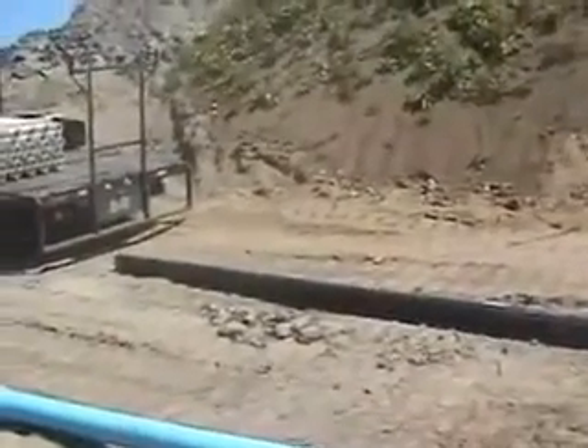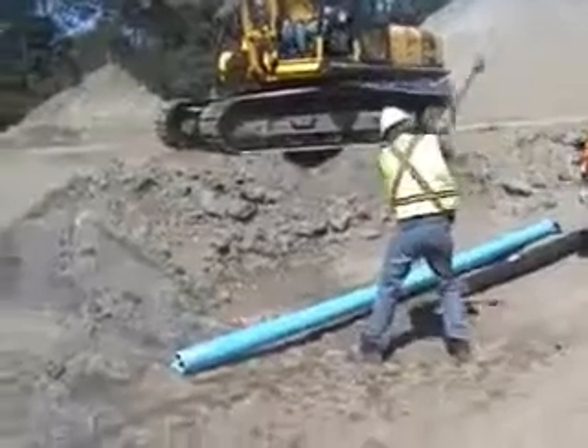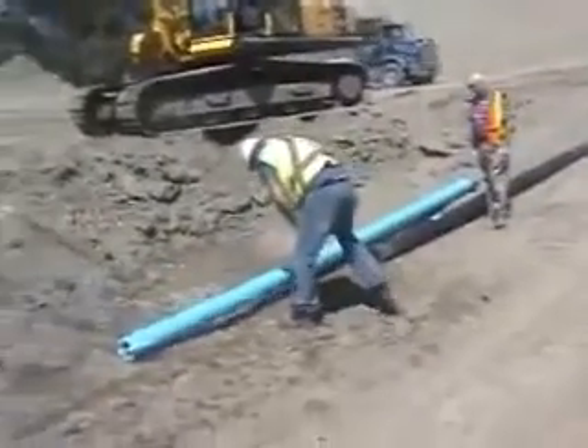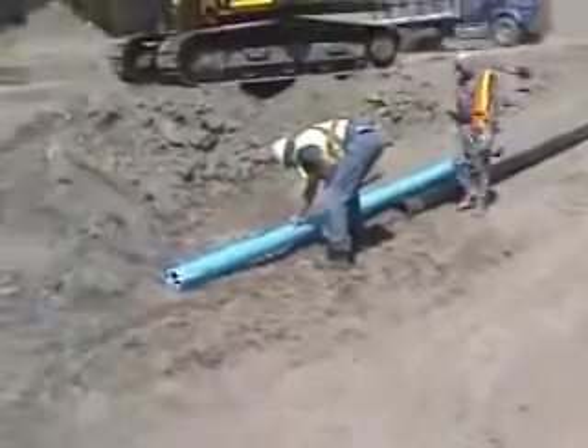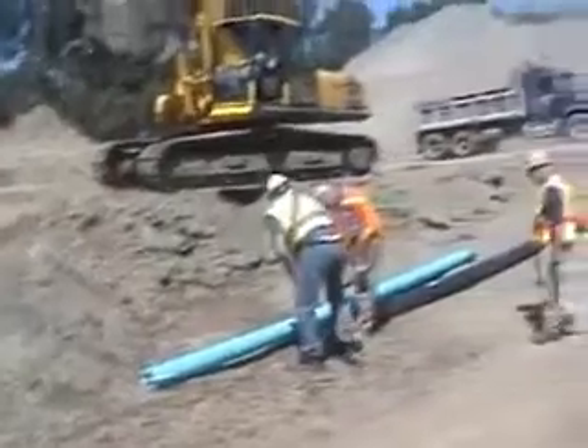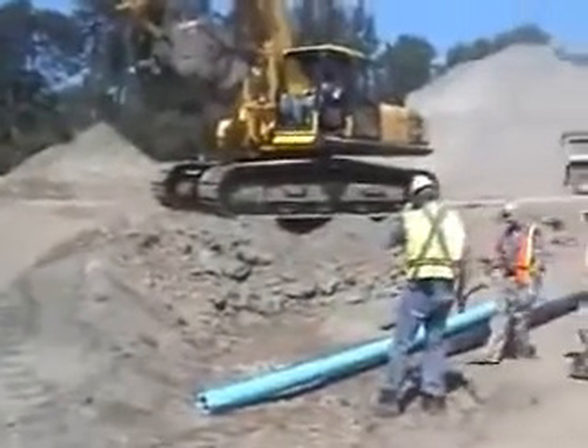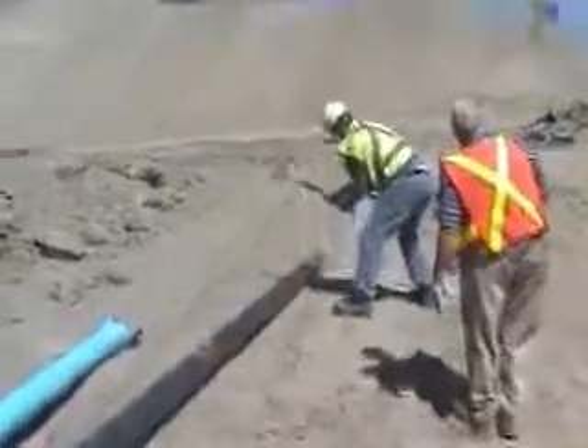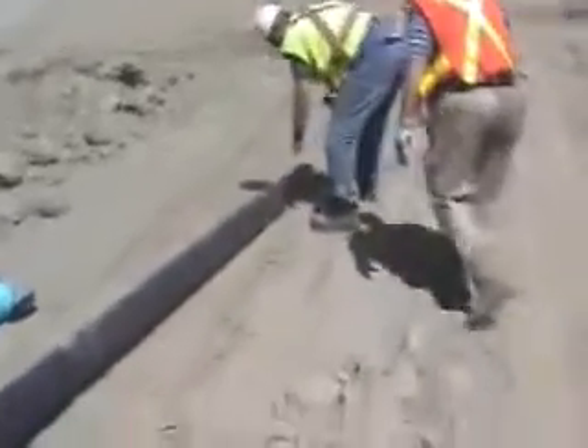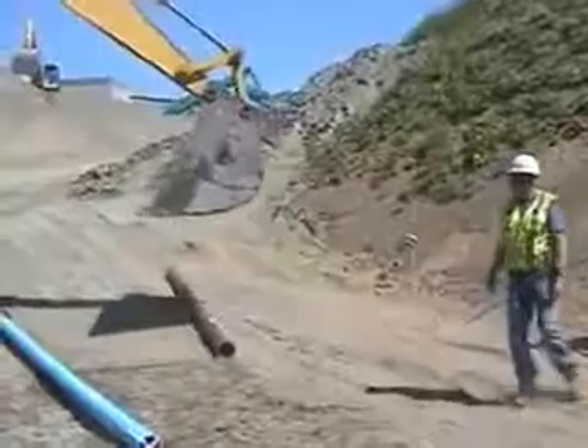New 6-inch samples of Bionax and ductile iron were brought to a sand pit for this demonstration. The initial test involved hitting both pipes with a sledgehammer. The sledgehammer bounced off of the Bionax pipe without causing any damage. When the ductile iron was hit, the pipe became dented and the inner cement mortar lining broke off locally.